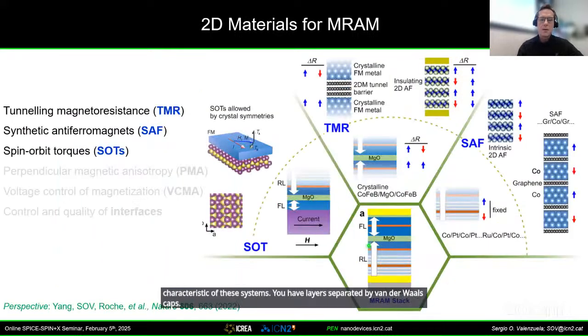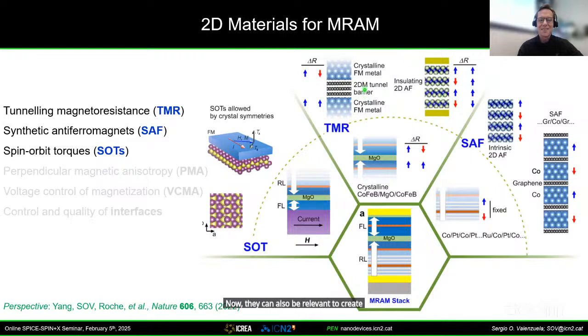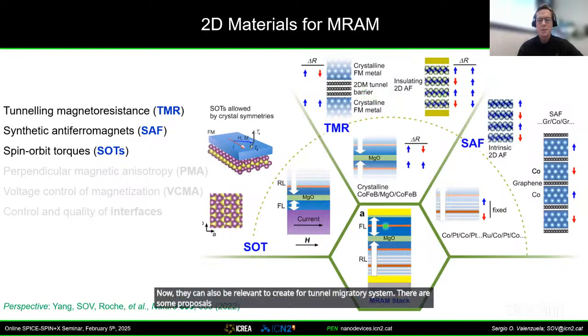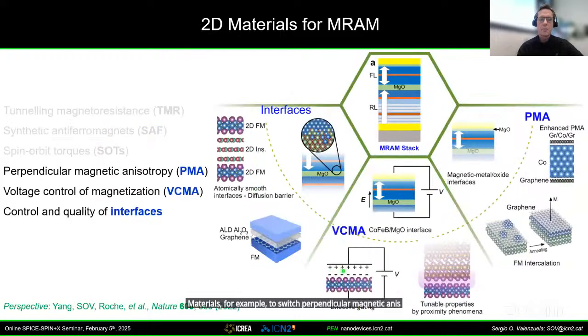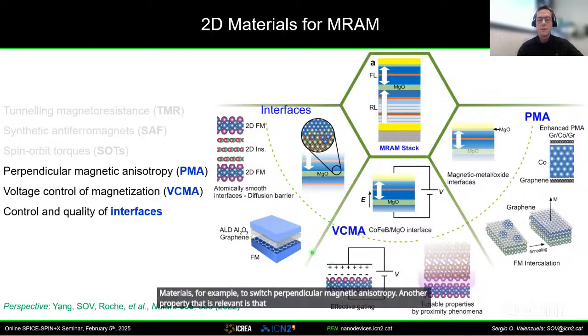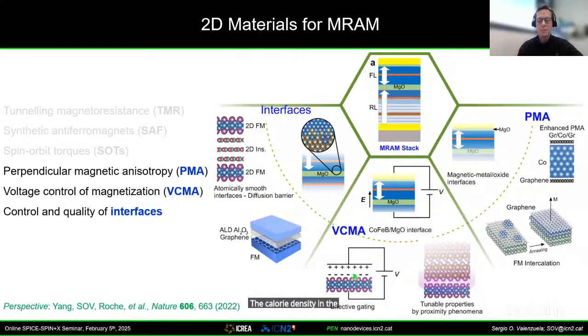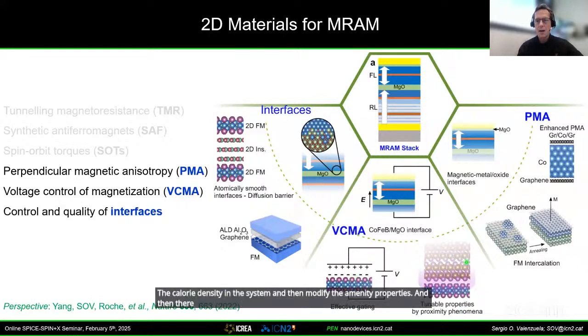Now, they can also be relevant to create better tunnel magnetoresistance systems. There are some proposals of materials that can replace MgO. You can also create synthetic antiferromagnets or have spin orbitors with symmetries that you don't find easily in the 3D materials, for example, to switch perpendicular magnetic anisotropy. Another property that is relevant is that of voltage control of the magnetic anisotropy, because these can be monolayers. You can apply a gate voltage and modify the carrier density in the system and then modify the magnetic properties. And then there is the proximity effect that I mentioned before.